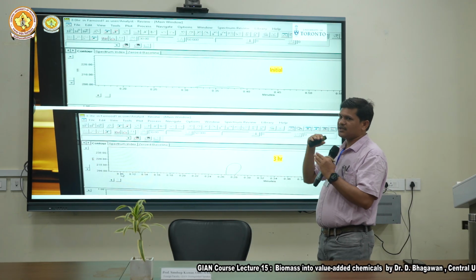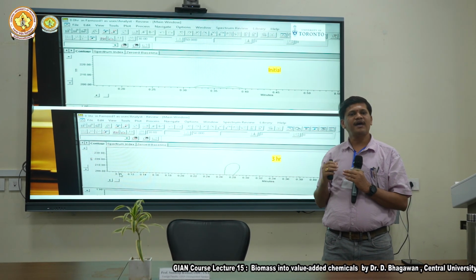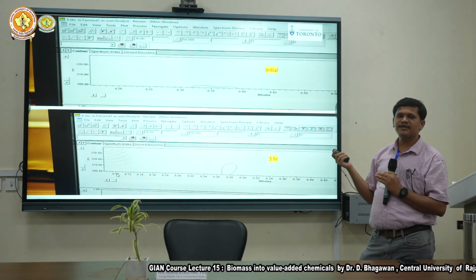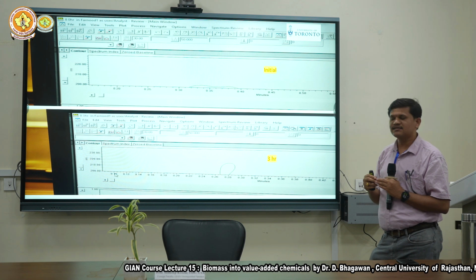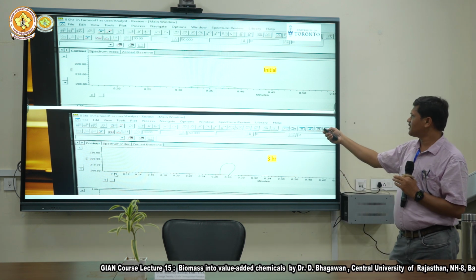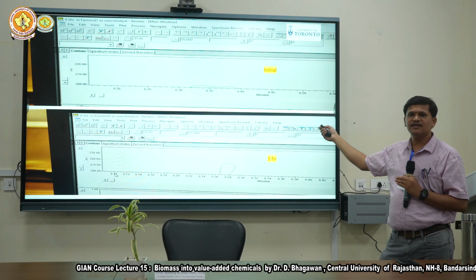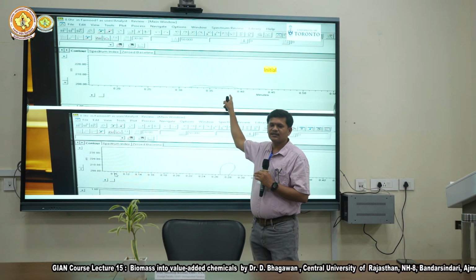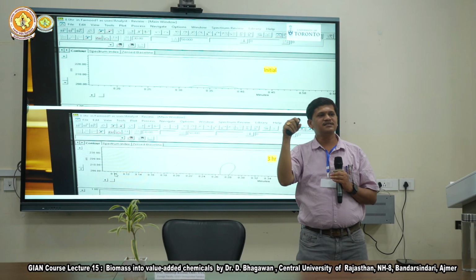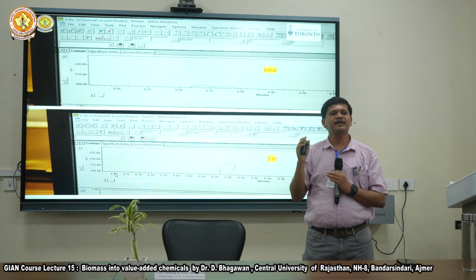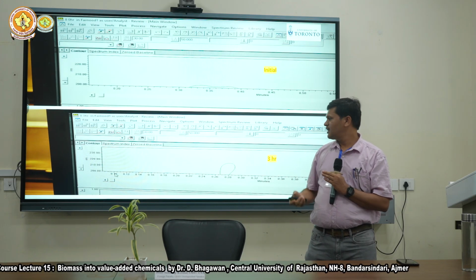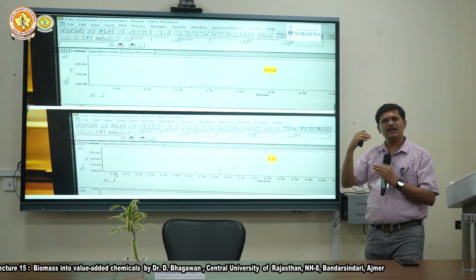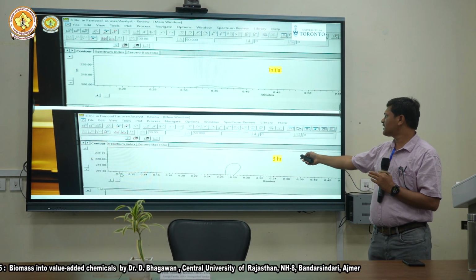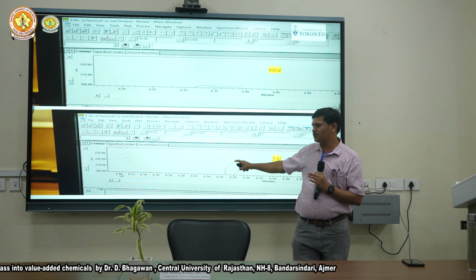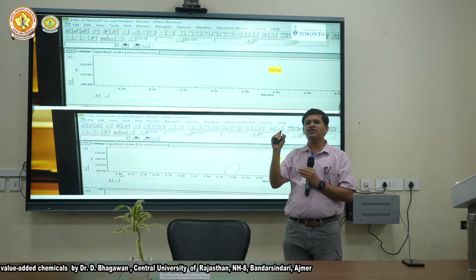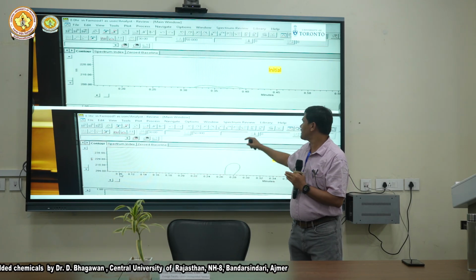So I just want to show how this new compound formation has been identified. You can see here this is the UHPLC peak, which we use for organic analysis. If you see the retention time at 0.32 to 0.39, we have a small peak at the initial stage. Once we add this catalyst into your solution, obviously it will start interacting and reacting with your lignin compound. Next, when we start the reaction under photocatalytic intensification at 3 hours, you can see the peak height. This height gives you the concentration of that particular compound at that particular time, so you can compare these two.